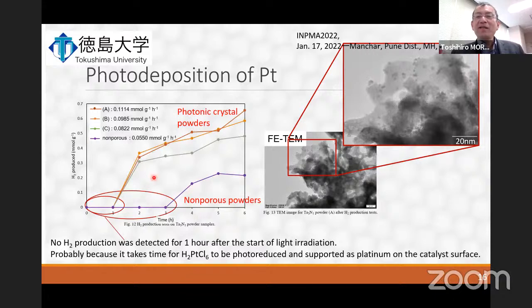Deposition of platinum as a co-catalyst onto the tantalum nitride is necessary for hydrogen production. Photodeposition of platinum was conducted under irradiation of the 100 watt xenon lamp. No hydrogen production was detected for at least 1 hour after the start of the light irradiation, probably because it takes time for hexachloroplatinic acid to be photo-reduced and supported as platinum on the catalyst surface, I guess. FE-TEM photographs showed that platinum particles of 1 or 2 nanometers in size were well dispersed over the tantalum nitride powder here.